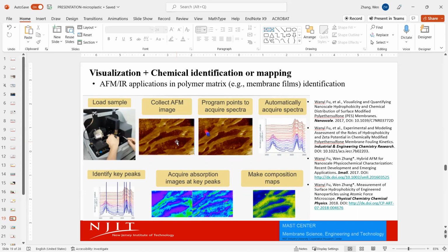So we are very interested, not merely us, but industries like the membrane industries. When they fabricate a certain membrane, they coat the membrane with additives, and they wonder where the additives are located, or what kind of chemical additives are out there, or what their distribution on the membrane is. So when you perform AFM mapping, you can see their morphology, no problem. Secondly, we also wonder what this polymer matrix is. Are they polyamides, or polystyrene, and where they're located. So we use this AFM to detect their signals at different places. The red and blue dots indicate the locations where the tips are actually engaged with the sample surface. Then we can map, or perform so-called chemical mapping. And this gives very good information about the chemical compositions of the matrix.